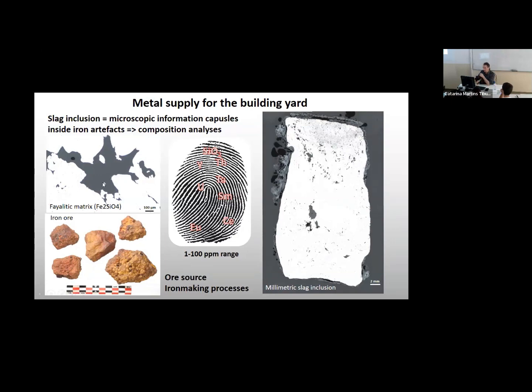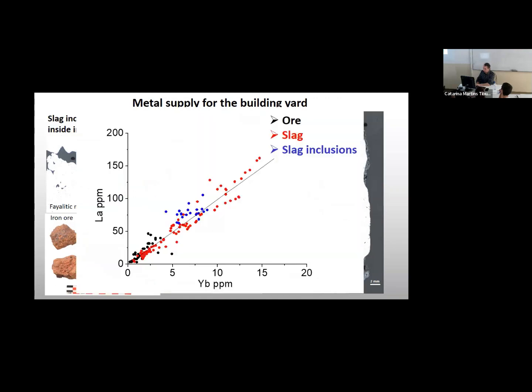I already spoke about slag inclusions, the impurities that are inside the metallic matrix of ancient, medieval iron up to the 19th century. And they really bear some kind of digital print of the ore, because when you reduce the iron ore, you will form these slag inclusions which have basically the same composition. And so if you use a different ore, then you would have slag inclusions with a different composition. There were analyses and experiments made about 15 years ago, so this is a method that is 15 years old.